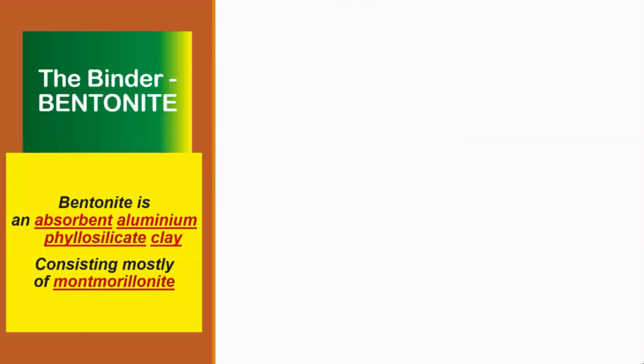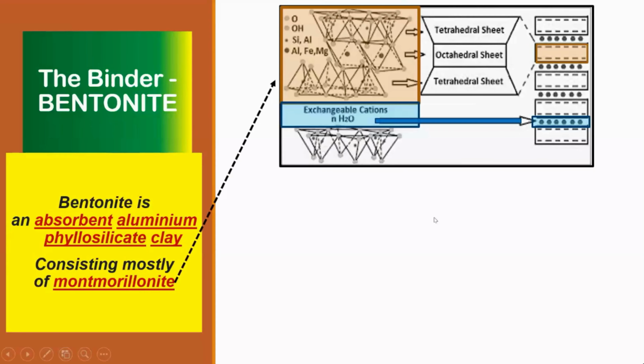Now let us get into the ingredients of the sand mix. The basic binder is bentonite. In chemical terms, it is an absorbent aluminum phyllosilicate clay consisting of montmorillonite. Montmorillonite is a mineral which is existing in this form. It has got exchangeable cations sandwiched between two layers of